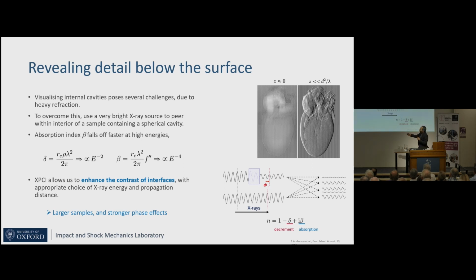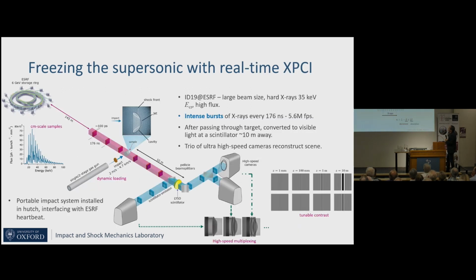So we can play a trick. We can go to very, very high energy, which means that we don't have to worry about absorption. High energy X-rays mean we can put large amounts of materials in the way. And because of the way that the absorption and the phase effects change with energy, what it means is as we go to higher energy, we get stronger phase effects. So there's our technique. Now, the trick is then putting these two together.